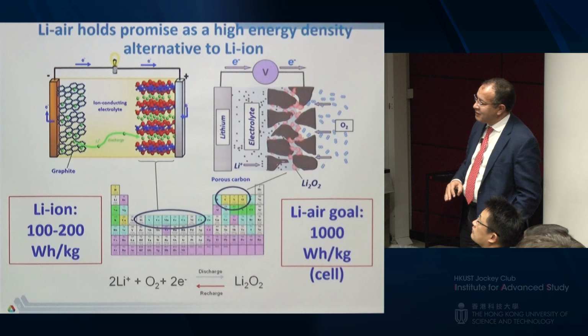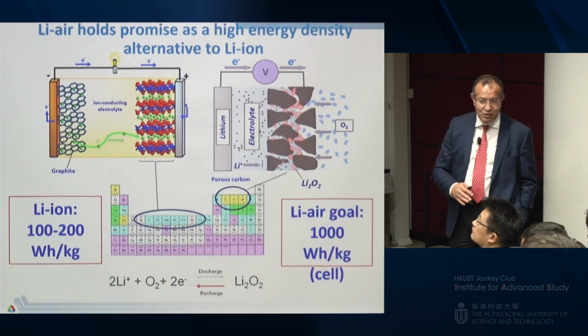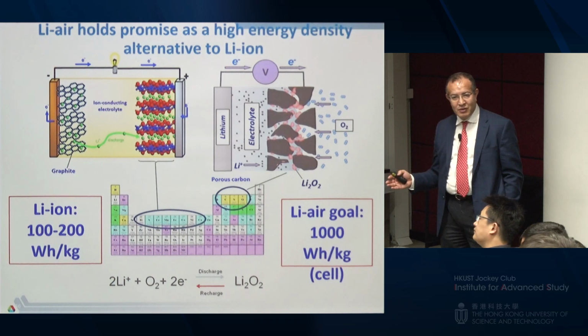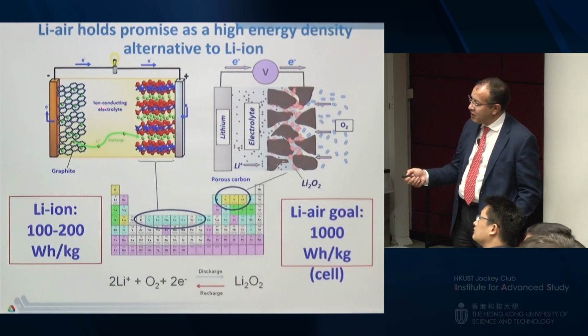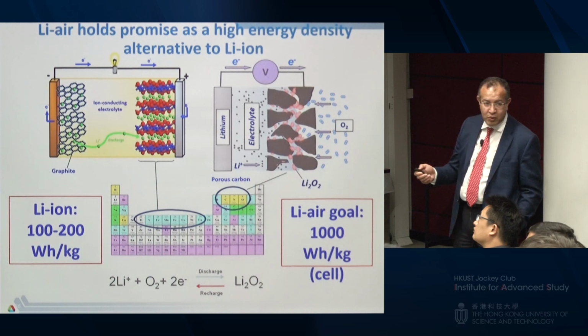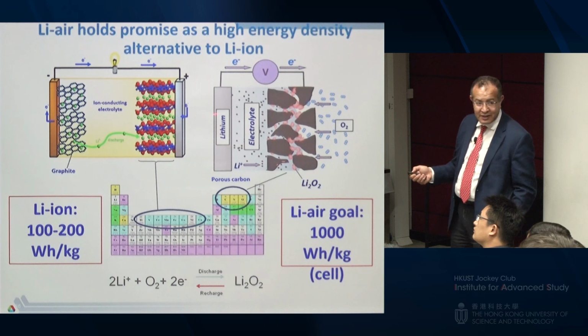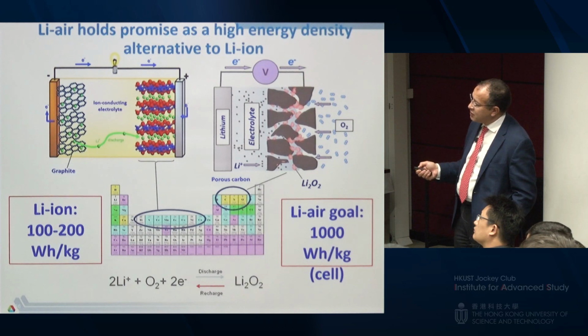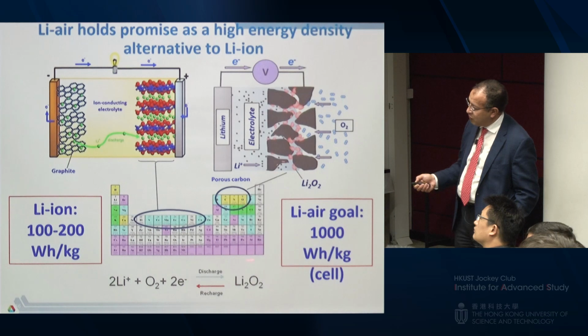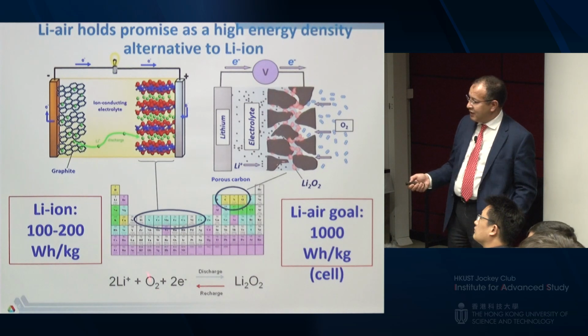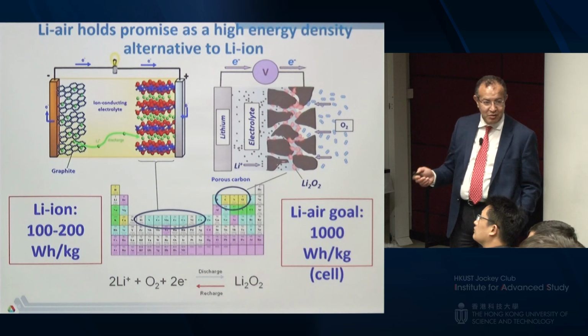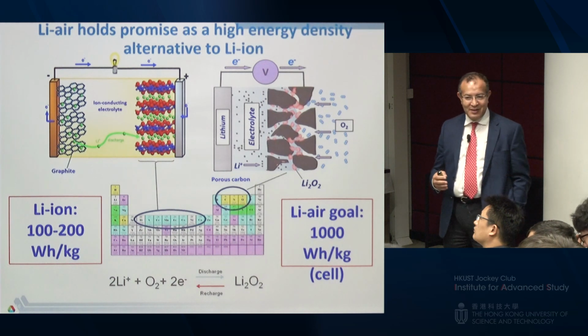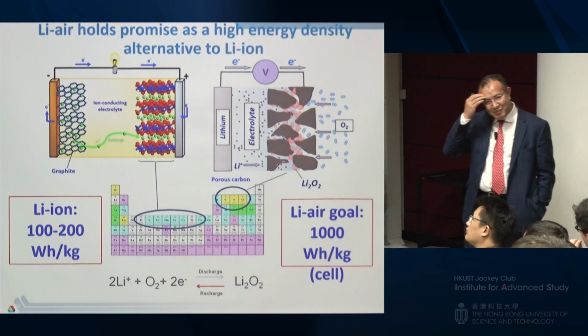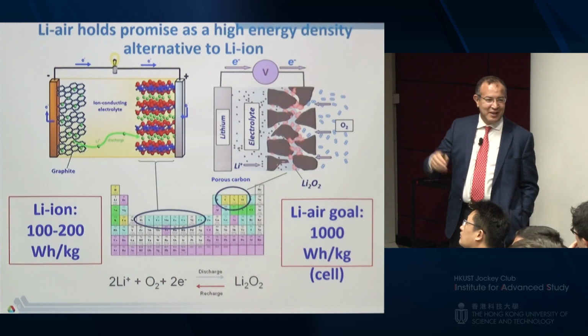Okay, so now the last part is lithium air. Obviously, lithium air has a totally different configuration versus lithium-ion. Lithium-ion is an intercalation process between carbon and metal oxide. Here you have an electrode, which is porous carbon, and you put a catalyst. So basically what you do, you send oxygen, you have 2 electron transfer to form lithium peroxide. That reaction gives you 10 times the energy of lithium-ion. Now, that's very serious, 10 times. If you can just tap into 30% of that reaction, you get almost 3 times.